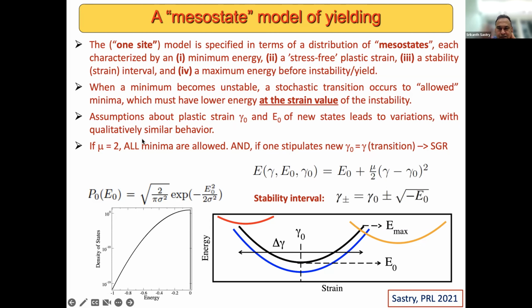And so I won't describe the model in more detail. In some limit, it reduces to the SGR model. But basically, the essential ingredients are a distribution of energy minima, a description of how the elastic energy changes, which is basically like a simple quadratic form, a specification of the stability interval in strain over which a given minimum or a mesostate is stable. And here the key ingredient is that this stability range is assumed to depend on the depth of the minima.